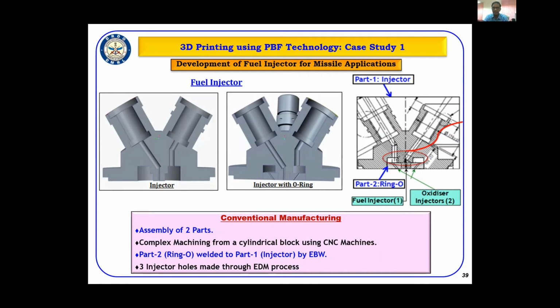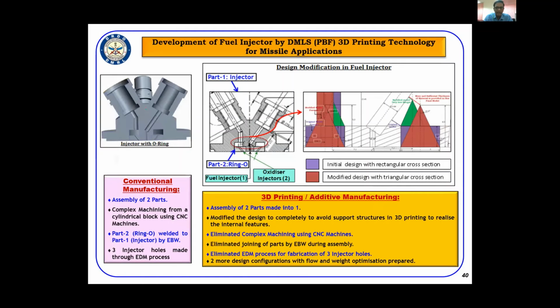This component has been taken up for 3D printing. And initially, as I mentioned, it is necessary for us to look into the design features of this component, make necessary design modifications to make it suitable for the 3D printing. And in the 3D printing, what we have done is we have assembled the 2 parts made into one. That means we have eliminated the welding aspect of this component and modified the design to completely avoid the support structures.